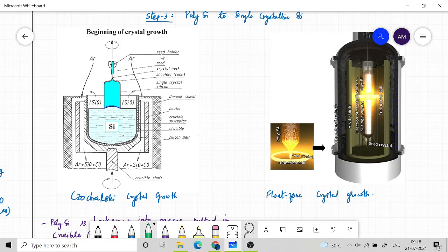As you lift it up, it gets cooled in a slow fashion, and the atoms get into the right place inside the crystal, because there is a position where energy gets minimized, and automatically they take those positions. That is the crystalline structure we discussed yesterday, two FCC lattices interpenetrating each other.